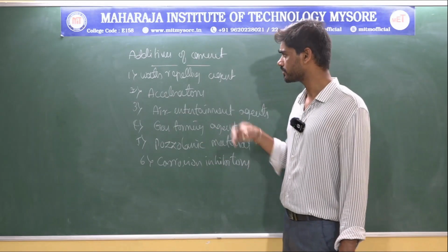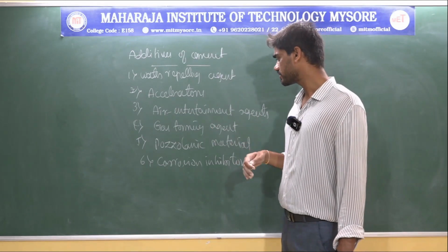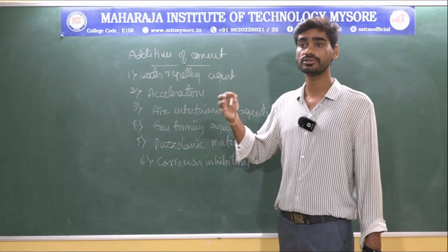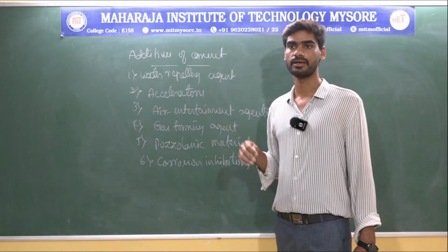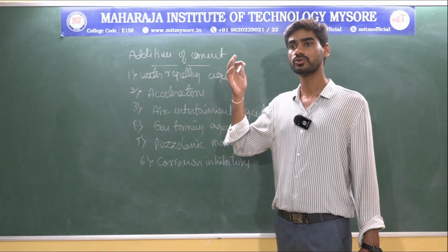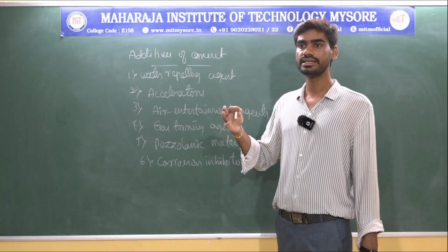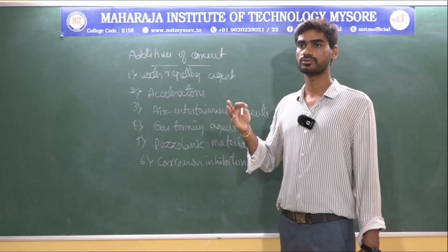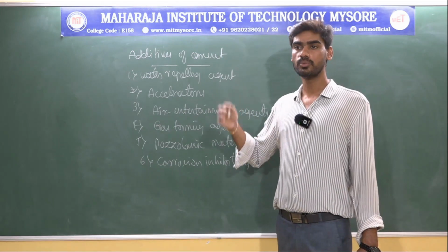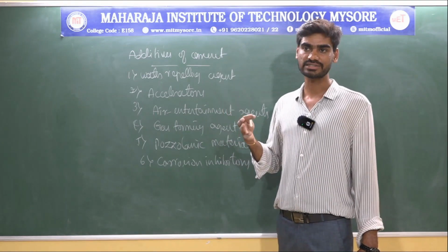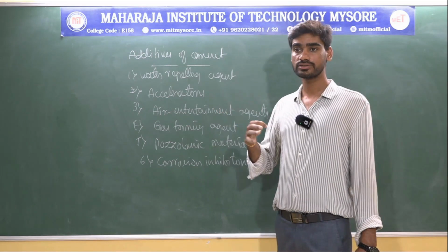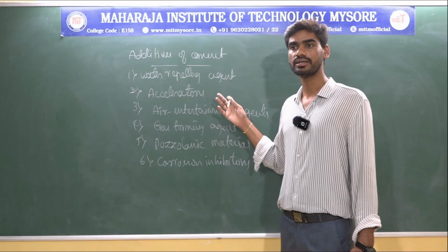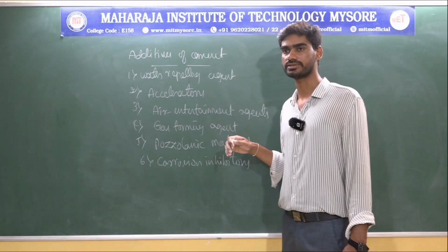So when we come to the fourth important additive, gas forming agents. These are added to cement in about 0.005 to 0.02%. This one is basically added to produce gas, which leads to lightweight, sound or heat insulation. For example, aluminum powder is commonly used as a gas forming agent. It releases hydrogen bubbles by reacting with calcium hydroxide, which is formed during hydrolysis of C3S and C2S.